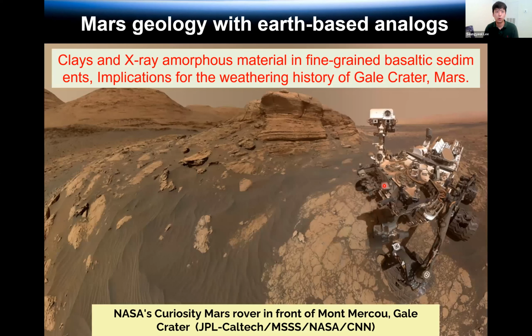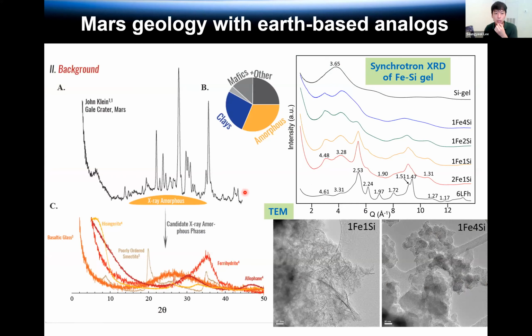So I am also involved in a Mars geology project. So I'm mainly interested in the clay and amorphous phase on Mars. Yeah, this is the rover Curiosity XRD pattern from the Gale crater area. Actually, this XRD hump led to the opaline phase, and this is a reference diffraction pattern to explain this opaline phase. Okay, based on the rover data, XRD and XRF data, actually this phase has lots of iron and silica composition. So iron silica gel is very important for understanding this phase.